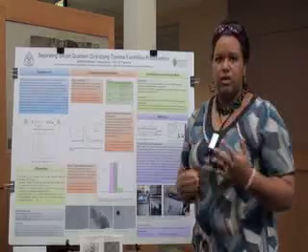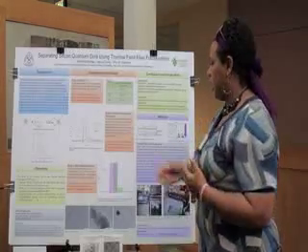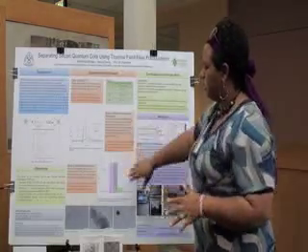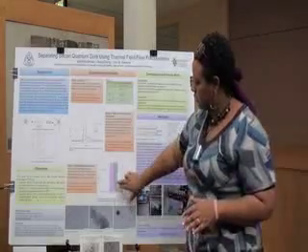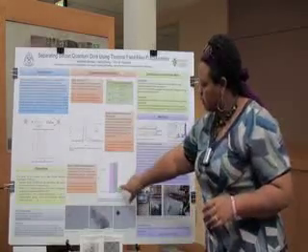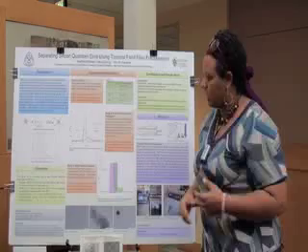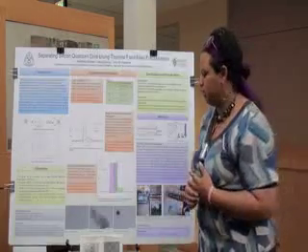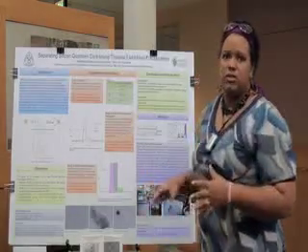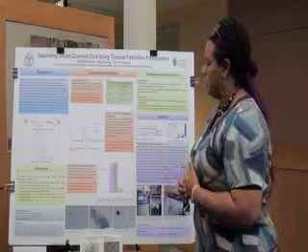The third part of the experiment was to collect fractions. So I used a delta T of 100 degrees C, and I collected 3 different fractions. I collected the first half of this peak here, the second half of this peak here, and the last and final, this small peak that comes out separate of the thing. And then I took TEM images of them to determine what's actually coming out of them.